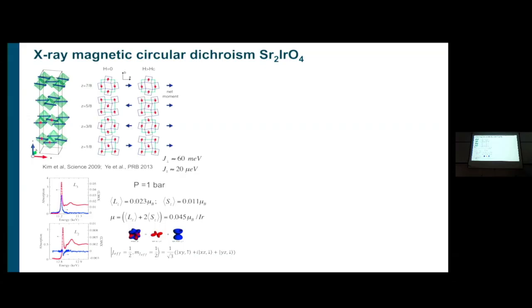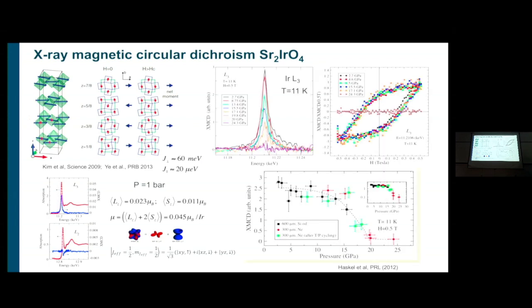And here we see again that if you look at the L3 and the L2 edges, you see this is very large, this is very small. Look at the scale, this is 3% XMCD on the blue. At the L2 is like 0.3%. So a factor of 10. That means there is a large orbital moment, and in fact the orbital magnetic moment is larger than, actually equal to, the spin moment, which is 2 times S. So the wave function of these iridium atoms is very complex because the spin and the orbits are coupled, and you actually get something like this, which we don't have time to talk about.